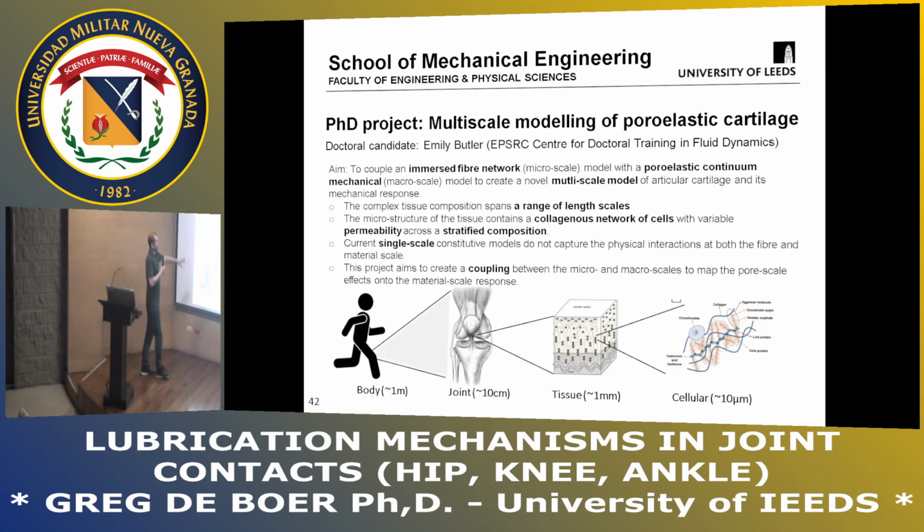So this is really quite difficult because what we model in a continuum type model assumes that it's consistent. The material is just a solid with some fluid inside of it. It doesn't have any information about this fibrous interaction. The way that we account for those is through the stiffness tensors and the permeability. These are the material parameters of the model.